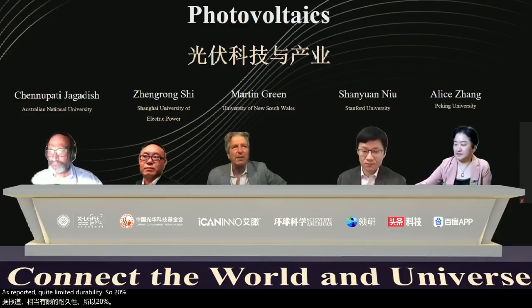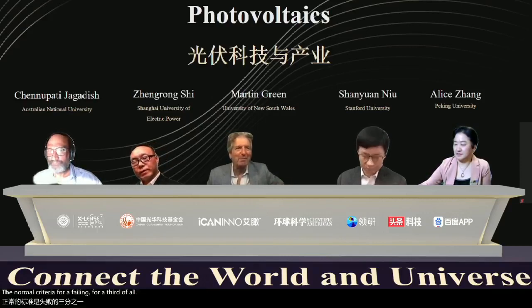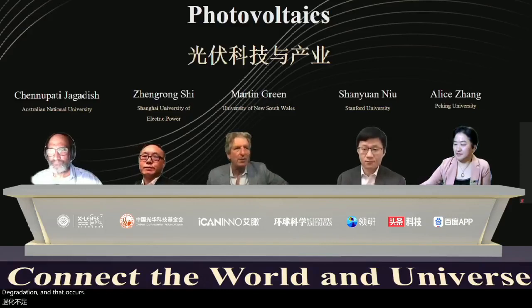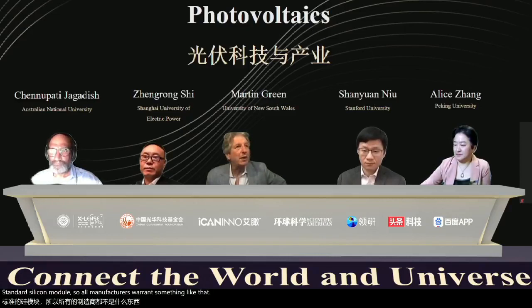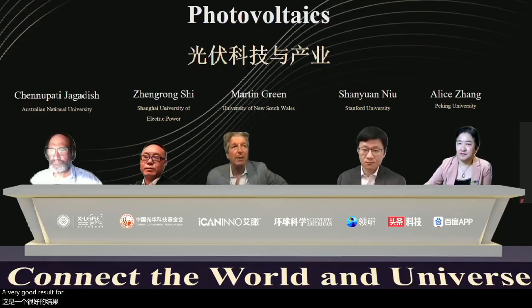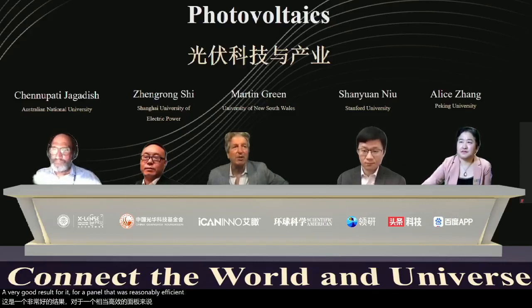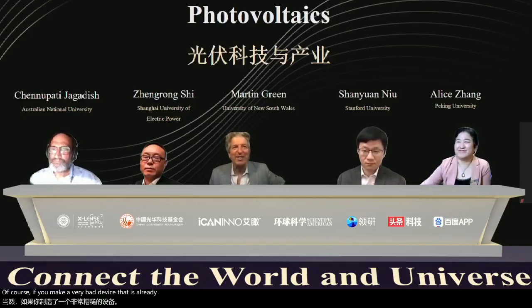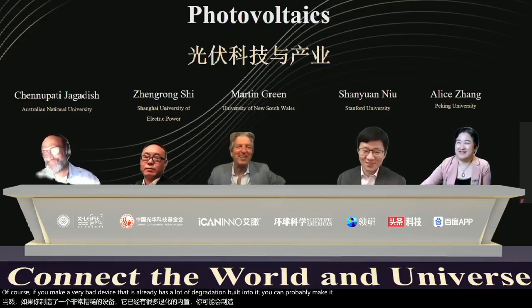20% degradation is the normal criterion for failing for a photovoltaic module, and that occurs after 25 or 30 years with a standard silicon module. All manufacturers will warrant something like that. With the perovskites, you're talking, like, 2 months would be a very good result for a panel that was reasonably efficient. Of course, if you make a very bad device that already has a lot of degradation built into it, you can probably make it last a lot longer. But if you make a really state-of-the-art device, you're stuck with rapid degradation. So it's orders of magnitude improvement that are required.